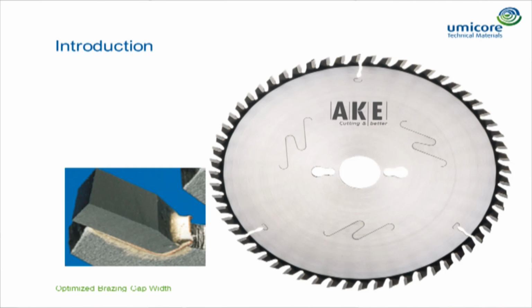This can be normal brazing filler metals, but also some special brazing alloys, which can be seen here. Here you can see the steel blade, and here the cemented carbide tip, and in between is the brazing filler metal, and this is a special brazing filler metal. You can see some red color, some copper in between.